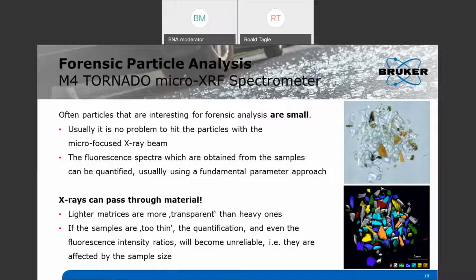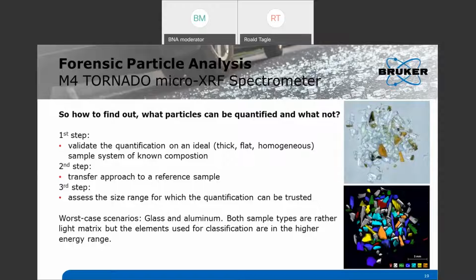And this is a problem since X-rays can pass through material. So small glass is not only transparent to visible light, but also to X-rays. And if these samples get too thin, our quantification algorithm, as well as the net peak intensities, will be giving wrong values. So the question will always be which particles can be quantified and which are too small. And this is a pretty straightforward process.